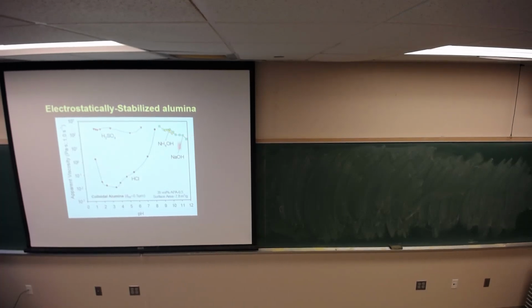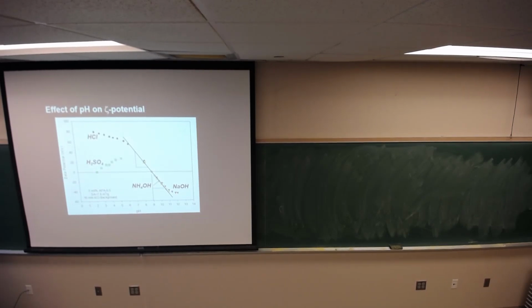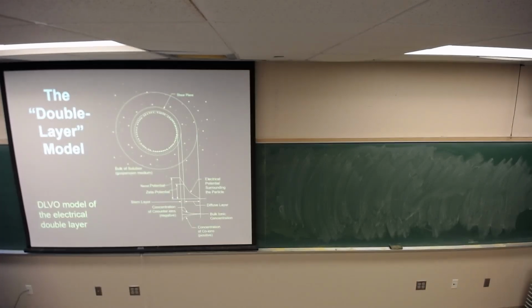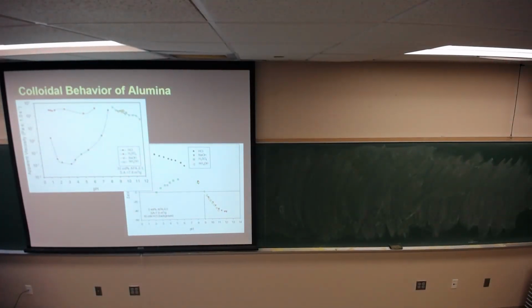So this curve and this data and the zeta potential data and the viscosity data, they appear to be not entirely consistent, okay? But in fact, they are perfectly consistent and correct for the volume concentration of particles. And you should become familiar with that. Good? Any questions?